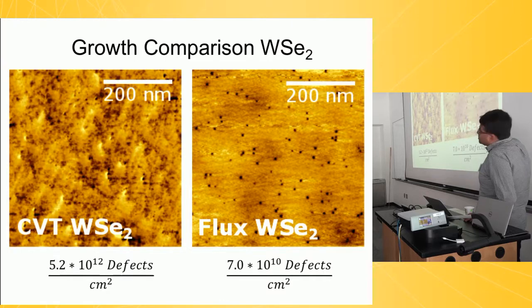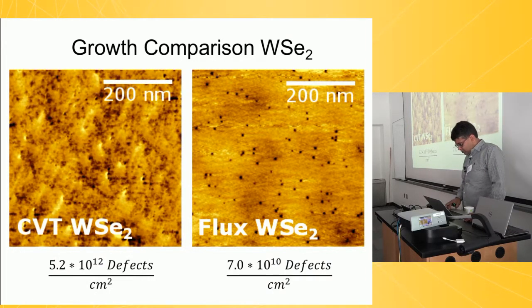That was MoSe2. This is WSe2. Do the same thing. CVT WSe2 has just a boatload of defects. It's 5 times 10 to the 12. And flux WSe2 is actually the best crystal we've ever grown. These are sort of the best that I've ever seen in anybody's crystals, on the order of 10 to the 10 defects per square centimeter. We are still about 2 orders of magnitude away from graphene, but 2 orders is better than 4 orders, which is what it was earlier.